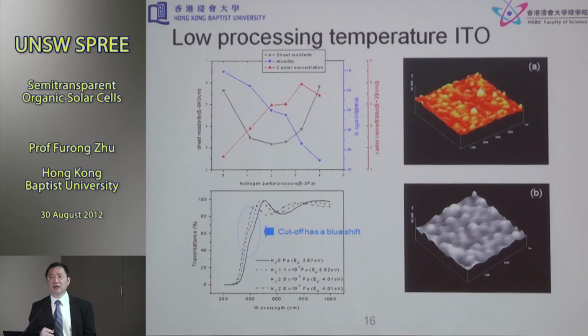In most cases, if you've done ITO, ITO is typically prepared in the presence of argon and oxygen media, because you want to get a sputter done in this. And in this work, we introduce a very small amount of hydrogen species, serving as a reducing gas during the ITO deposition, because ITO is an oxide semiconductor material.